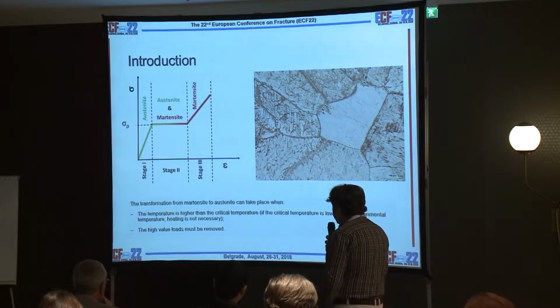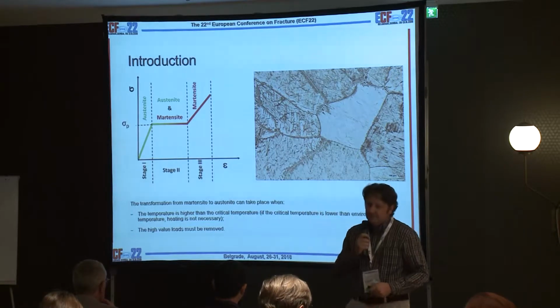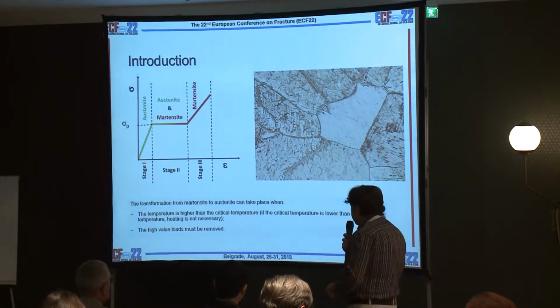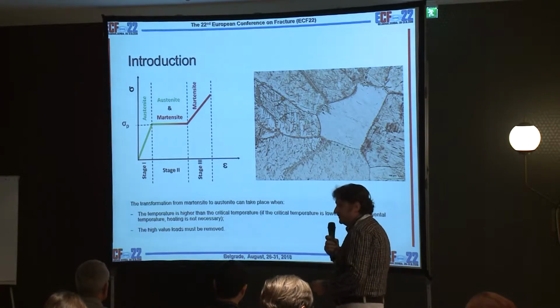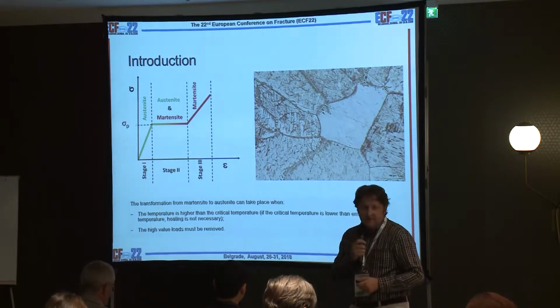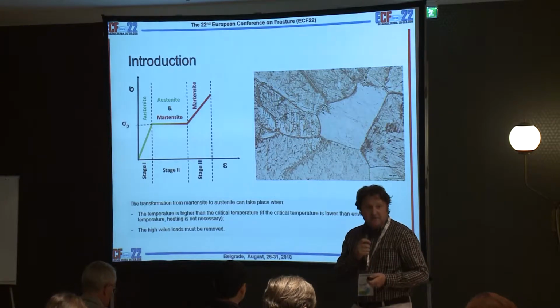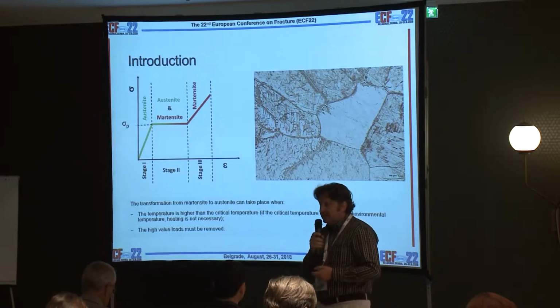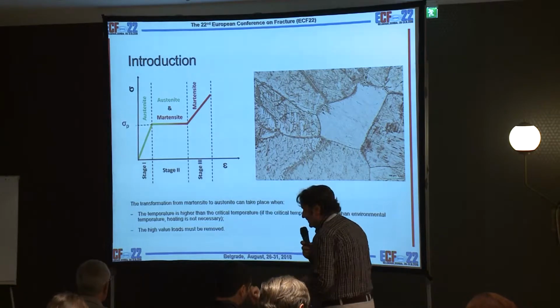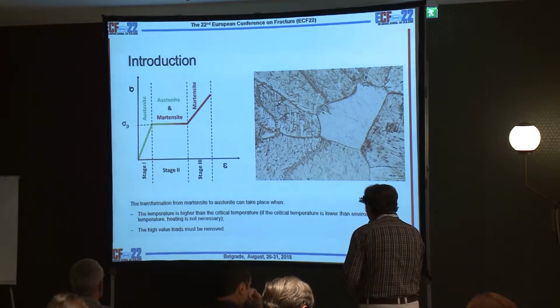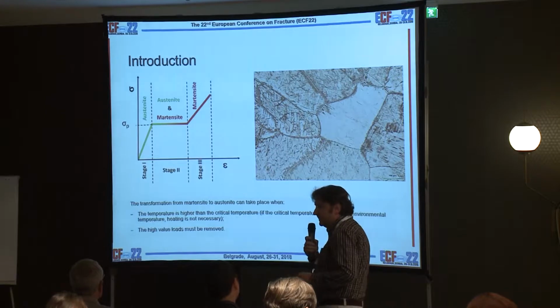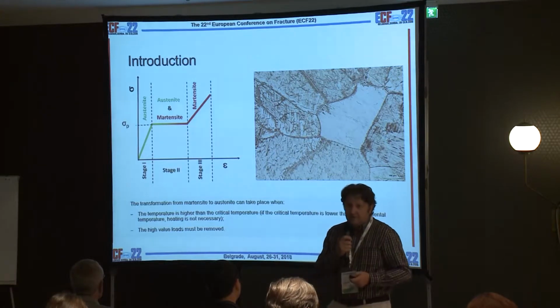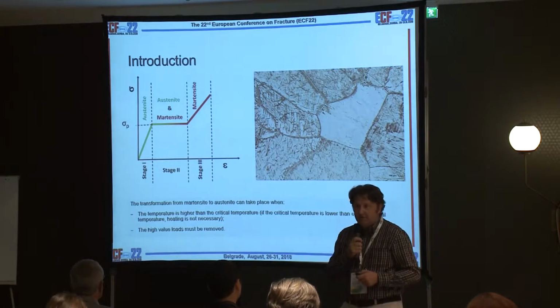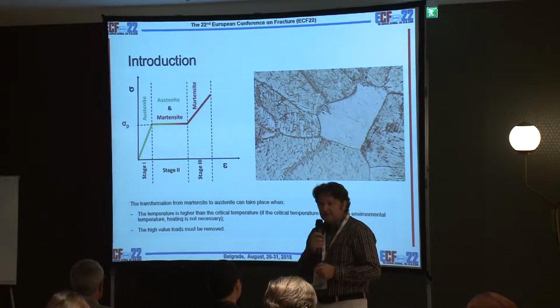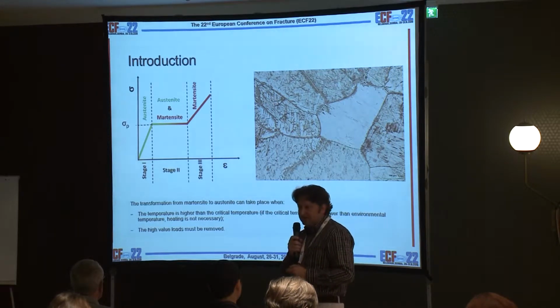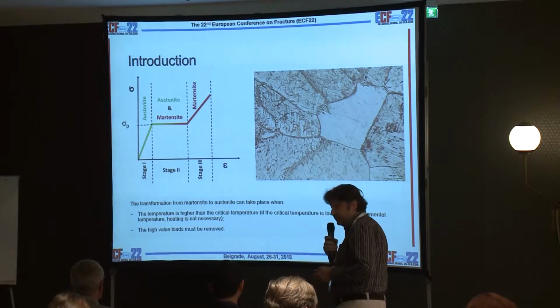We have two different mechanical behaviors. In the first one, the reverse transformation to get the initial shape cannot take place because the material doesn't have enough energy to recover its initial structure. But we can heat the material up to a temperature greater than the critical temperature. In this case, the inverse transformation from martensite to austenite takes place, recovering the initial shape.